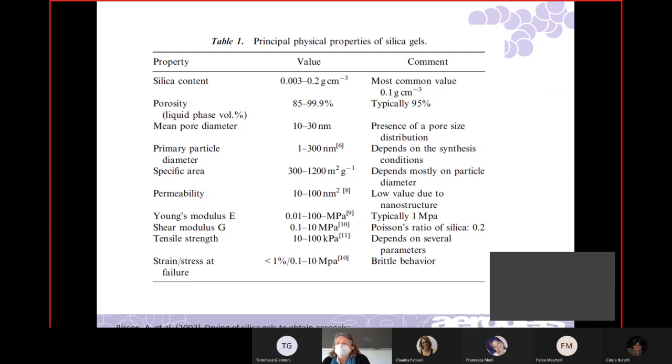Those are not properly dried and they tend to be very dense. So they'd be even higher than this, maybe 0.5 grams per centimeter cubed. They're very porous. Again, Mary talked about when you make them, they're full of air. I don't think we've ever made one that was 99.9%. Typically 95 is sort of where we are with them.